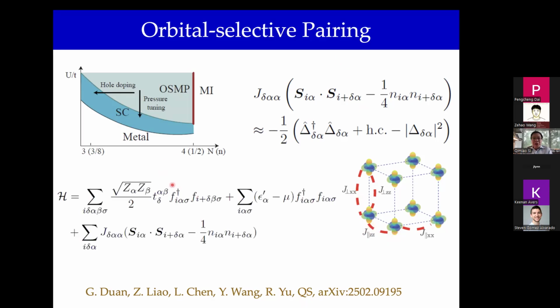And we put the multi-orbital Hubbard model in this effective t-J description, where the t part experiences the renormalizations in an orbital-selective way, as I already described for the normal state, and we keep these renormalization factors as calculated in the normal state. There's also an important detail, which is how the 3d z-squared orbital and 3d x-squared minus y-squared orbitals, how the crystal-field levels determine their relative separation. We believe that these details are actually manifested in a variable way in bulk materials, as well as in thin films, when, for example, the c-axis lattice constants are tuned by different amounts, and I'll come back to that.